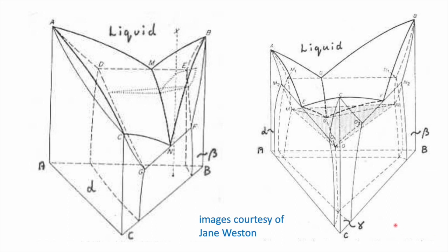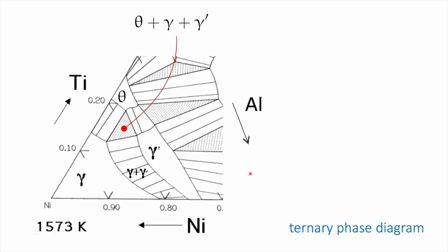So what we do instead of plotting A, B, and C versus temperature is we take sections of this diagram, ternary sections. And here is an example where we have a mixture of titanium, aluminium, and nickel. And these are the phases that are stable. Here, gamma of this composition is in equilibrium with gamma prime of this composition. In this triangle, we have gamma, theta, and gamma prime all in equilibrium, and so on.